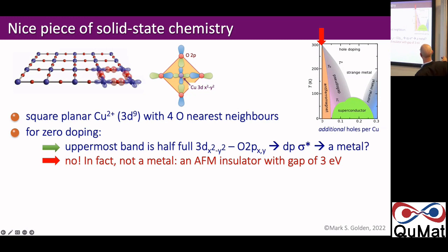So here's the phase diagram. As you add additional holes beyond this one intrinsic hole per copper, you get a superconducting dome appearing between about 0.05 and, depending on the compound, up to about 0.3. So the fact that superconductivity goes up is interesting. The fact that it actually goes down again is interesting. And this is the big challenge for condensed matter science to understand this phase diagram.